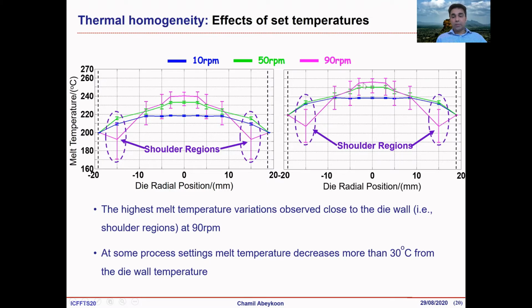So you could see the fluctuations at different locations are dependent upon the set temperature as well. So over here, this is the zero in the middle of the die, and this is somewhere close to the die wall. These fluctuations are huge here, but the lowest variation is in the middle. So the thermal behavior is really complicated.